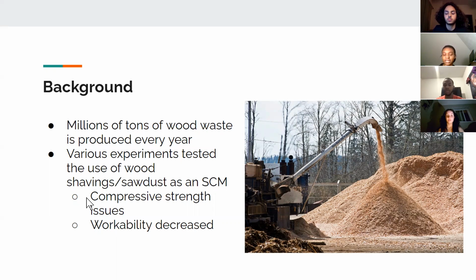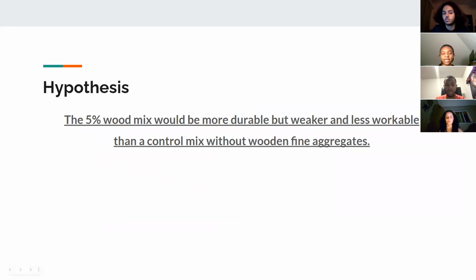Before conducting any tests ourselves, we familiarized ourselves with the experiments other people did to determine how wood would affect the properties of the concrete. The main issues that resulted were that the wood decreased workability and replacements greater than 8% led to compressive strength issues. All of this research led to our final hypothesis that the 5% wood mix would be more durable but weaker and less workable than a control mix without wooden fine aggregates.